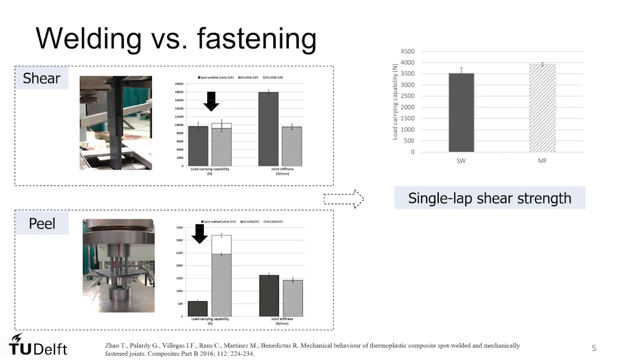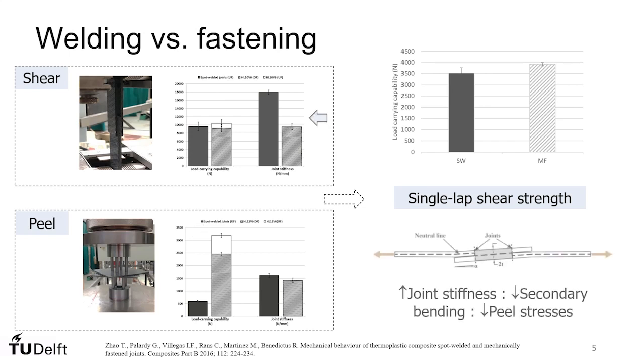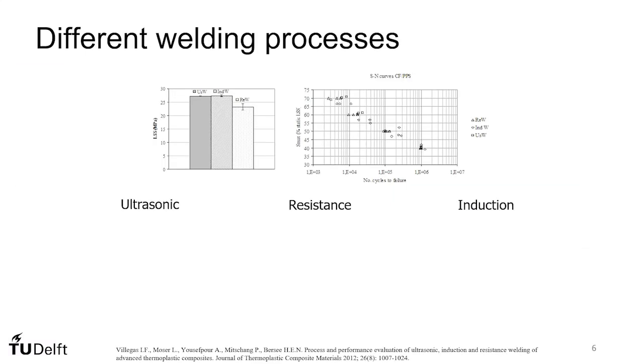case. But why? Well, if we go back to the shear tests, we see that the welded joints had a much higher stiffness. Consequently, secondary bending during single lap shear testing was lower, which resulted in lower peel and hence a more favorable stress scenario at each load level in the welded joints. Can we say this was a fair comparison? Let's look now at the comparison among different welding processes.